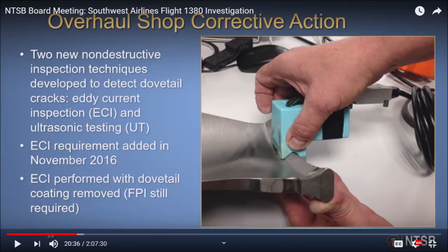There are several different types of overhauls: on-wing inspection and off-wing shop maintenance at different levels. Through a series of service bulletins and airworthiness directives, folks are now required to check these blades every 1,500 to 1,600 cycles. If you do an on-wing inspection, you are required to do an ultrasound inspection. If you do an off-wing inspection at 1,600 cycles, you're required to do an eddy current inspection. With eddy current testing, you run a magnetic field over a metal object, and if there's a crack, it disrupts the field and shows up on the test. Manufacturers have developed special tools to get these tests done on the fan blade dovetail sections.